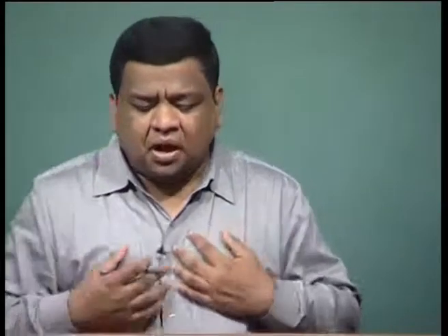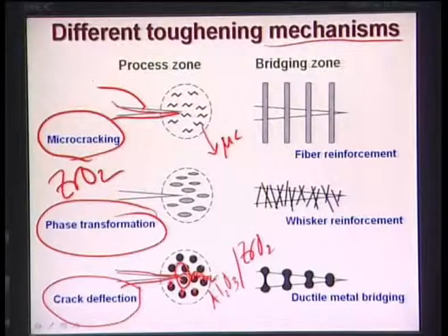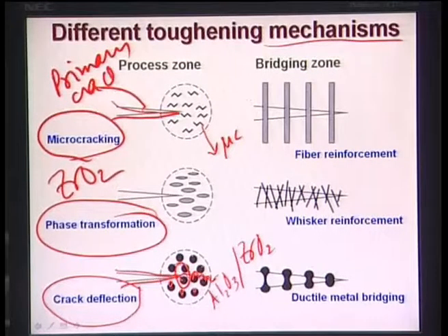Depending on the severity of your machining processes, all your materials are bound to have some smaller or finer size cracks in the material. Now, this is your primary crack, and your primary crack has a much larger length compared to the microcrack, that you realize first.